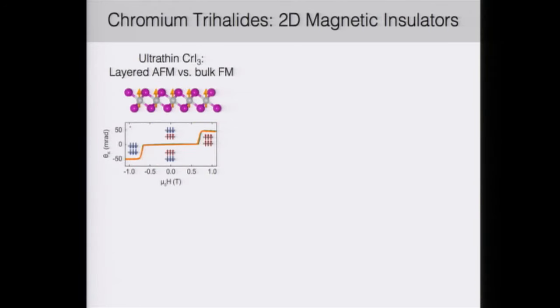So to summarize, the chromium trihalides are a class of 2D magnetic insulators that can be cleaved down to the monolayer limit where magnetic order still remains. We have one member, the ultra-thin chrome iodide, a layered antiferromagnetic phase compared to the bulk.